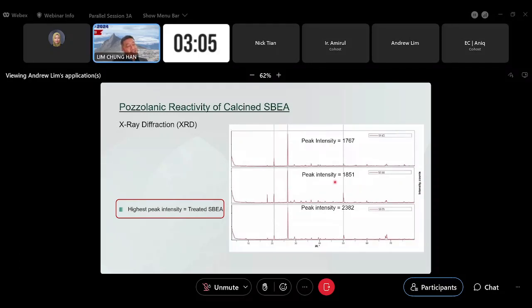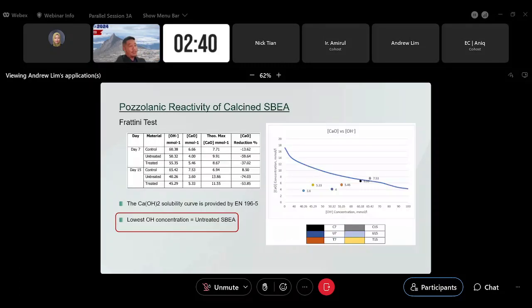So you can see slightly elevated levels of intensity. And finally, the treated one, you get the highest intensity. Okay, so if you look at it in terms of intensity, it's the treated one that gives us the highest intensity and hence a better performance. So that's the XRD result. And finally, we go on to the chemical test, the Fratini test.